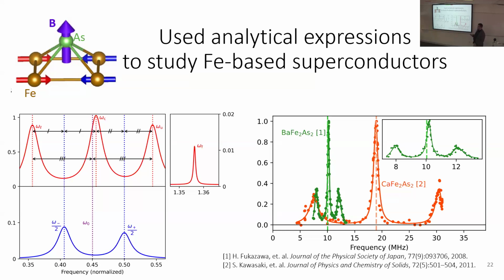There's 2 things going on here. This arsenic atom has a quadrupolar nucleus, and this large internally produced magnetic field is absolutely massive. It's on the order of a Tesla. And so it is perfectly suited to be studied by this research that we did of quadrupoles in a magnetic field. And so going back down here, I have this simulated spectrum that I calculated for a very specific value of asymmetry, quadrupole coupling constant, and internal magnetic field.